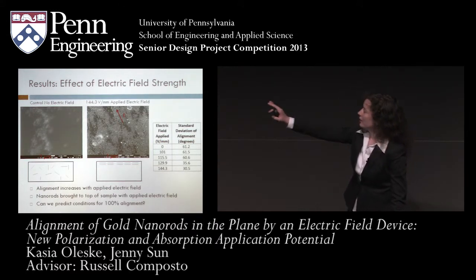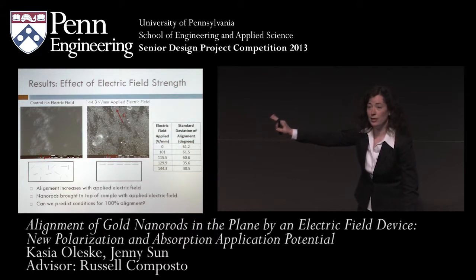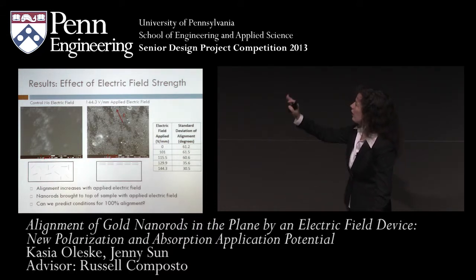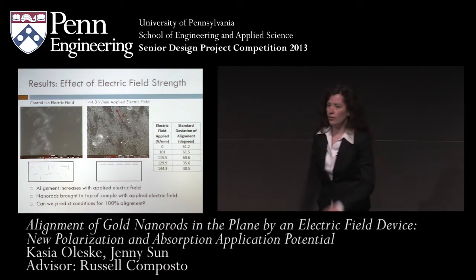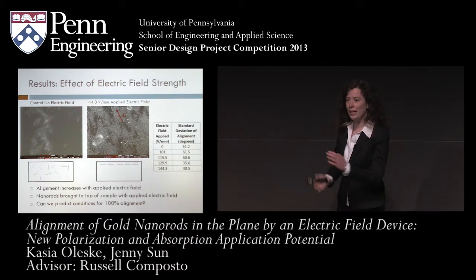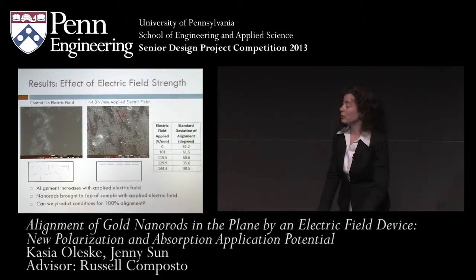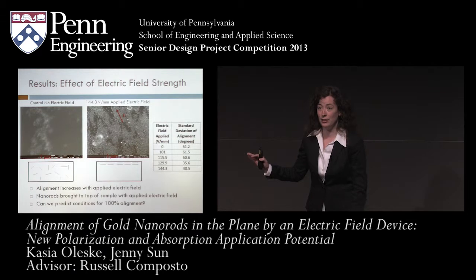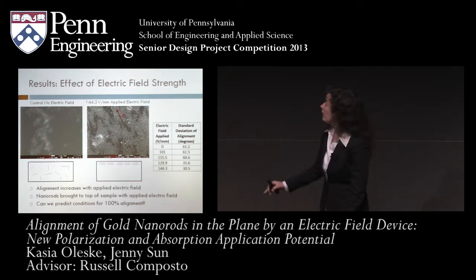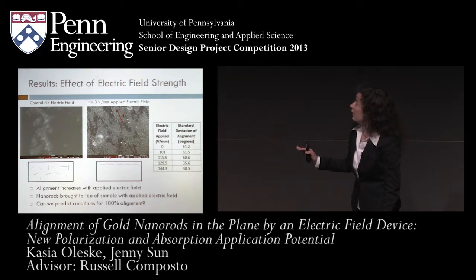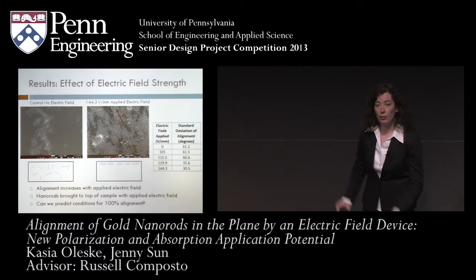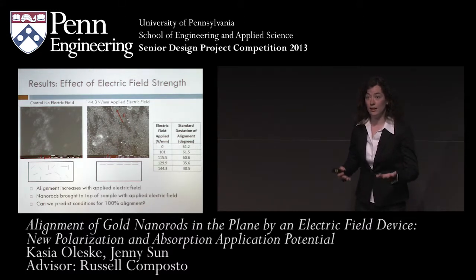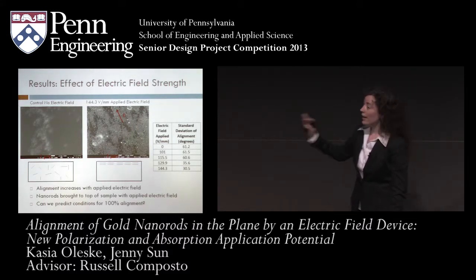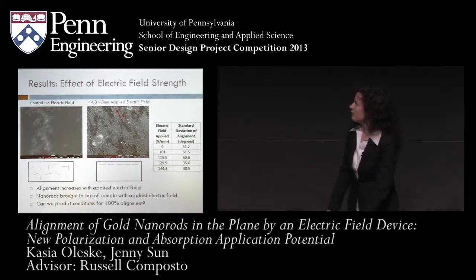And you can see in the schematic below the SEM image is a cross-section. And so when no electric field was applied, the gold nanorods were just randomly oriented throughout the thickness, which is why they look a little blurry in the image in the SEM. But when an electric field was applied, the nanorods were brought up to the surface because they're attracted to the electric field. Therefore, in the SEM image, they're much clearer.